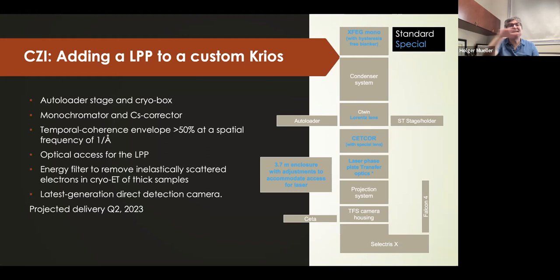There will be one plane in the specimen where the defocus is zero, and that leads to a flat contrast transfer function, which is very close to 1 over a very large range of spatial frequencies. In principle, we do not lose any information because the contrast transfer function doesn't have any zeros anymore, right? And this will be enabled by the combination of laser phase plate and spherical aberration correction.